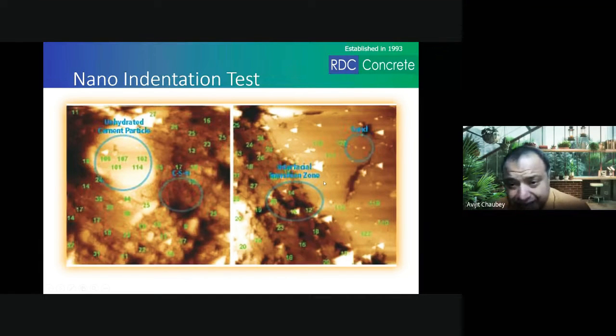And if you see on the other side, the aggregate gave a strength of 126, 110, 123. And similarly in the CSH, it is 16, 18, 23. So these were the numbers that they got while measuring the strength. Now, the reason you get higher strength with low water cement ratio is, if you see, there are many data you get from this study. First is, cement does not hydrate fully even if the water cement ratio is 0.5.